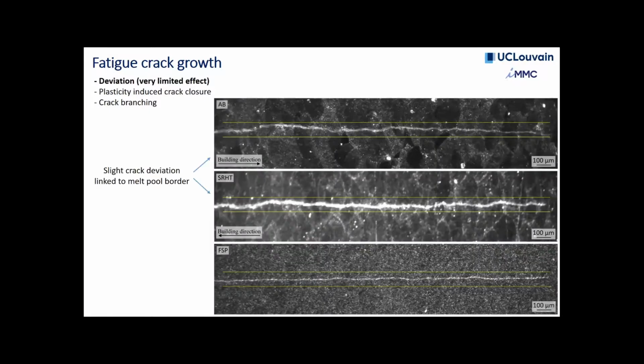And for that, we looked at different effects, the deviations. As you remember, I've shown you in this movie that we have very nice deviation with the as-built material. And this is also observed a bit in the stress relief heat treated material, and in the FSP material, of course, there is none of this microstructure, and so the crack propagates very straight. So this will be in favor of lower crack propagation in as-built and stress relief heat treated materials.